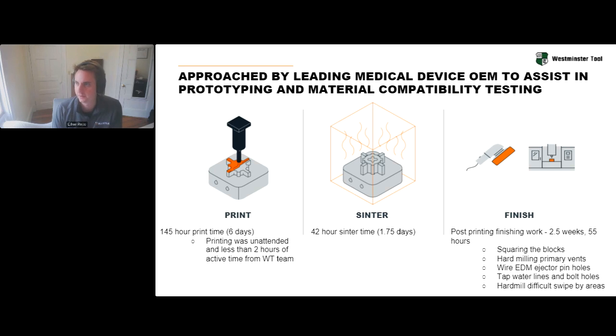They are medical, very precise inserts, so they did some finishing work here. They squared up the blocks. They did some hard milling on the primary vents to ensure it vented properly. They did the wire EDM on the ejector pins. They tapped the water lines and bolt holes, and then just a couple of the swipe by areas they did hard milling to ensure that the tool shut off correctly.